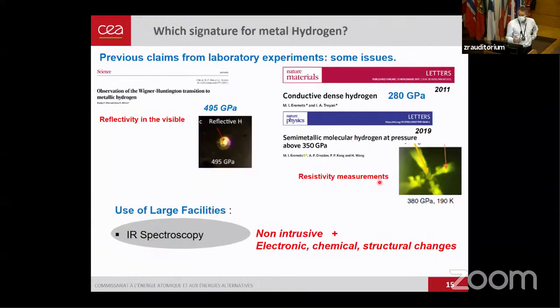Then which signature do you have to use for metal hydrogen? Previous claims for laboratory measurements, some have used reflectivity, like in the work of Silvera and Dias. No measurements, just showing a photograph. And there is a problem here. I will discuss that at 500 GPa, the diamond should be black. And there is a problem.